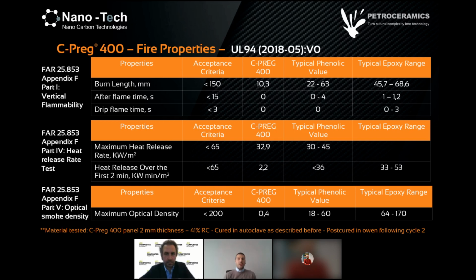Our laminates were tested according to FAR standard, the Appendix F, and they meet the requirement in terms of vertical flammability, heat release, and optical smoke density. The values obtained are comparable and even better than the ones with phenolic, as you can see, and way better than the normal epoxy flame retardant. As you can see here, among the acceptance criteria, Cpreg 400 has a very, very short burn length. It's not taking fire, basically. It has no ignition. And the heat release is also very low. What is also very important is that against the organic counterparts, there is basically no smoke. Because of 200 of acceptance criteria, optical smoke density, we have 0.4 against 18 to 170 of the other systems.